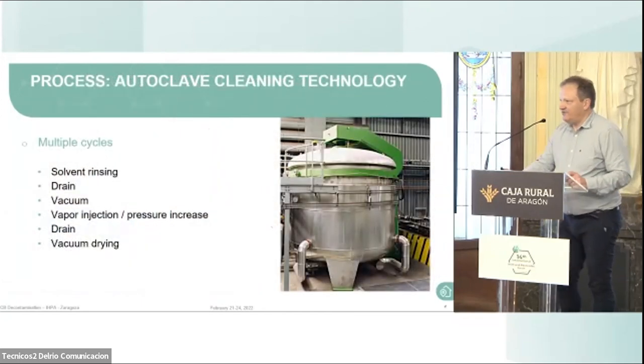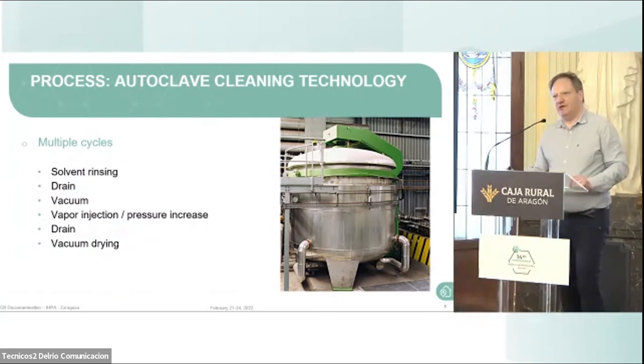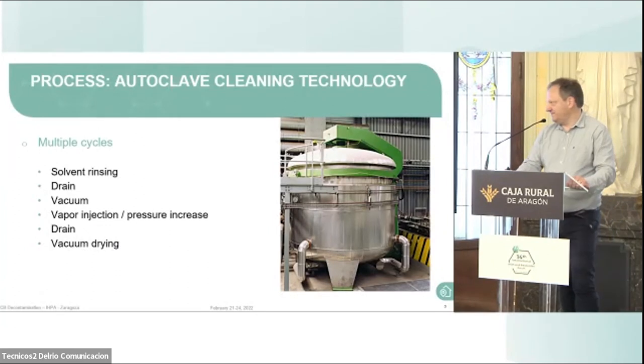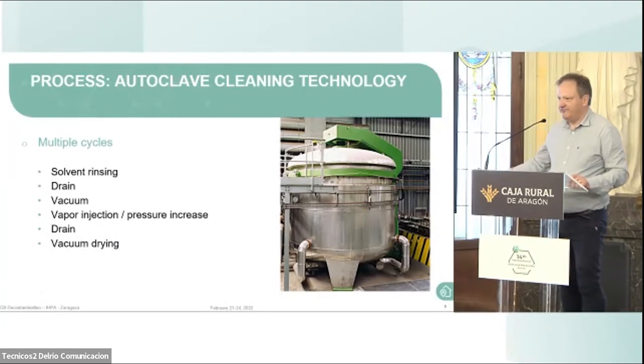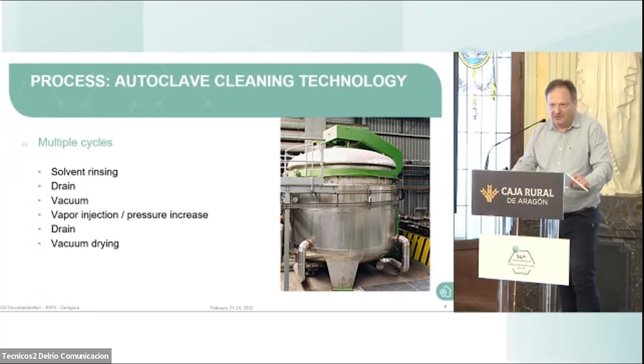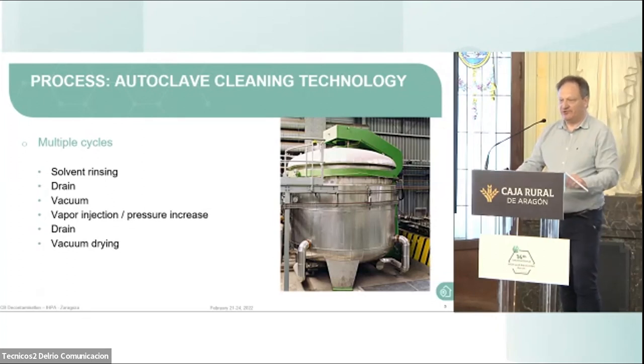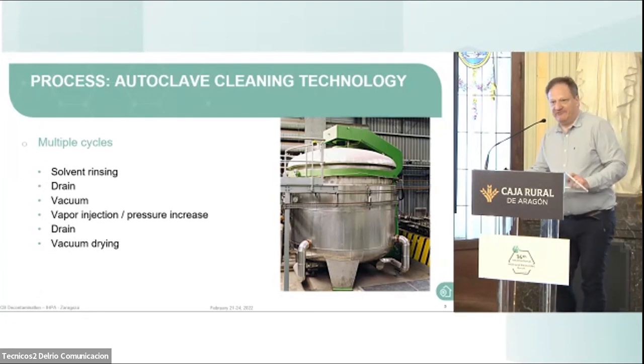This is our main installation. We are using the autoclave technique for cleaning the metals. It's a fully closed system. We are using a chlorinated solvent, and in the machine we put in the dirty materials, and then we have a spray of hot solvent, we have a vapor injection, we use temperature, we use vacuum to clean the metals. At the end, because we are working with solvents, we create a new problem, which is solvent emission. So we have to make a vacuum drying at the end before opening the vessel. So this system is working very well.